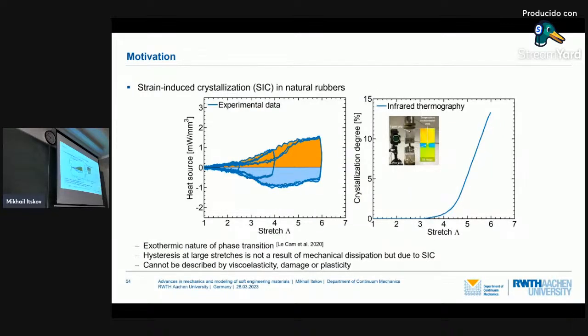This is exactly what I mentioned with thermography. In this way, we can measure the so-called heat source. And if we look, we see that, for example, at rather small cycling stretches, this diagram is rather symmetric. The amount of heat produced is equal to the amount of heat consumed by the melting of the crystals. At higher stretches, we have an asymmetry. This is due to the fact that crystallization is a phase transition, and for this reason exothermic. And due to the fact that we have no dissipation here, we believe that the hysteresis at large stretches in rubbers is not due to dissipation, but mostly due to strain-induced crystallization.